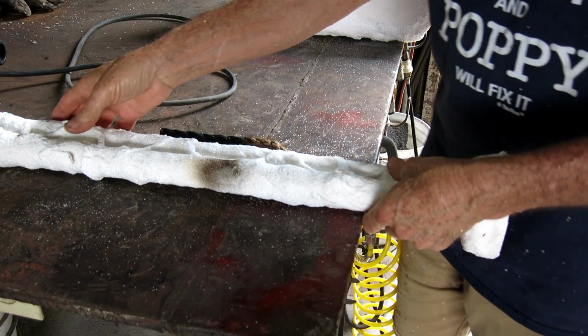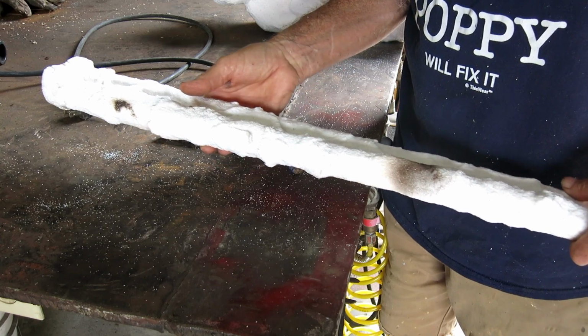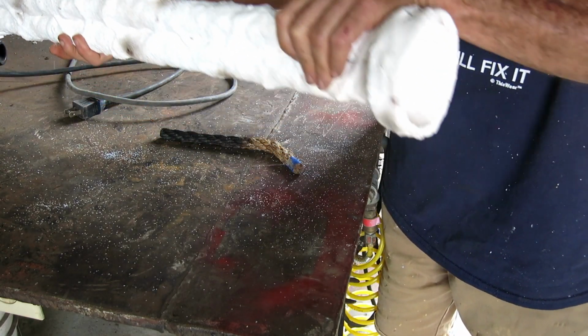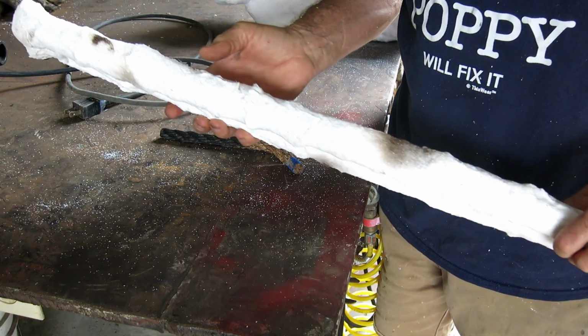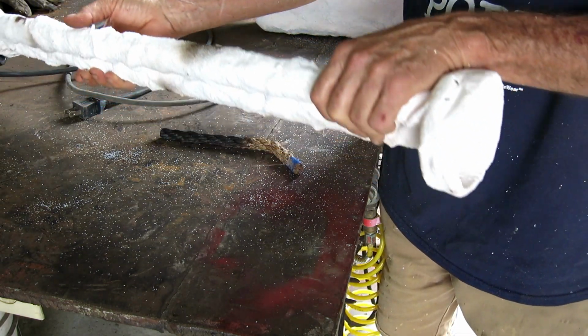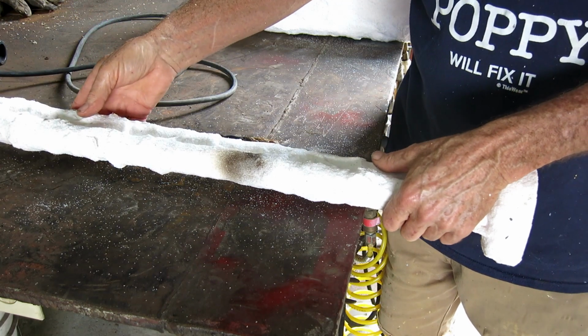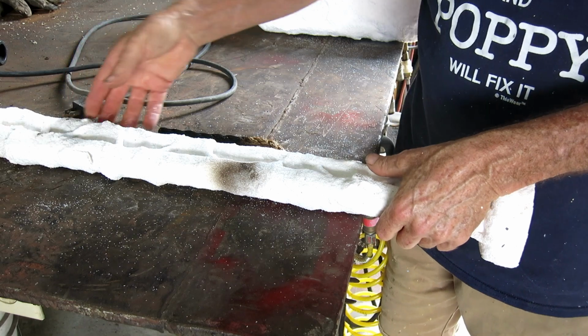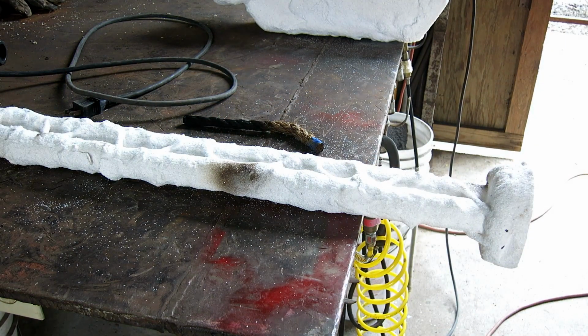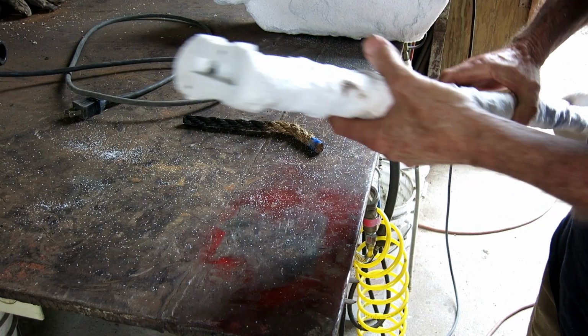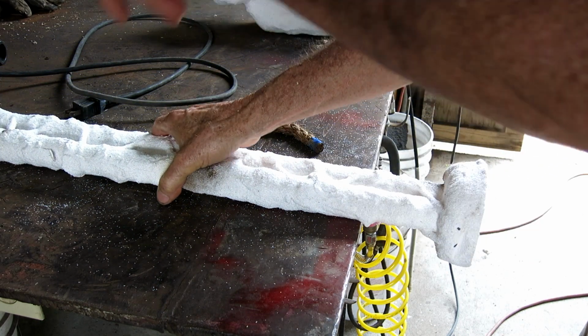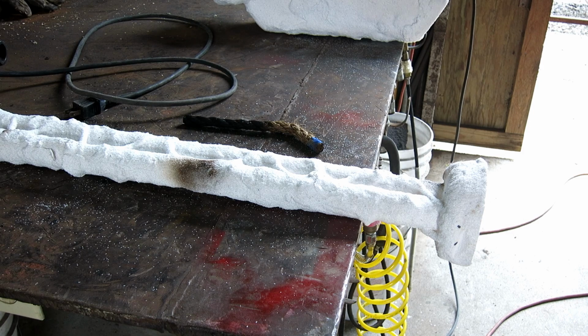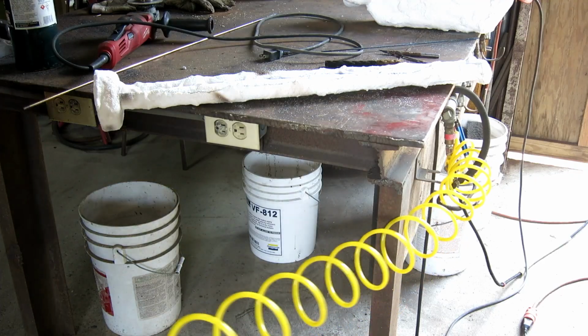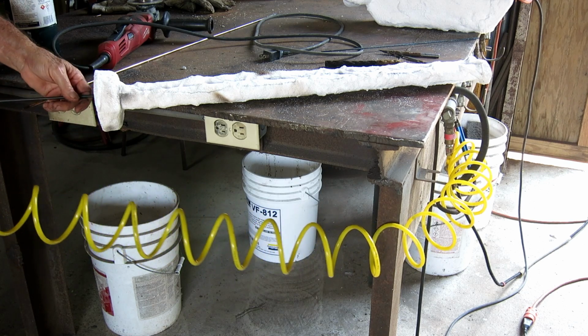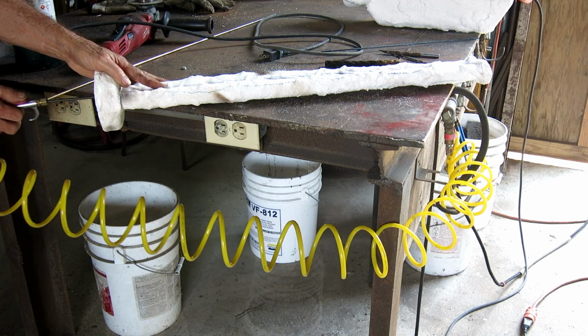But this one suffered a crack on the end, which is not the end of the world, and a lot of the rope burnt out, but not all of it. So I'm going to try to clean a little bit of it out with a piece of wire. I don't want to damage the inside, and I'll put it back in there and heat it up again, and I'll just keep doing that until I should be able to see, because I cut the bottom of the ceramic shell mold off a little while ago, or before I fired it. I should be able to see straight through, and once we can see straight through, then I'll put that bottom back on there.